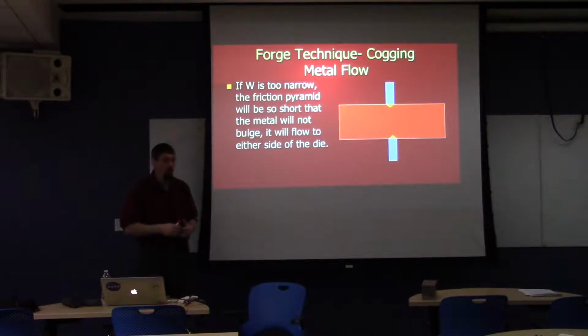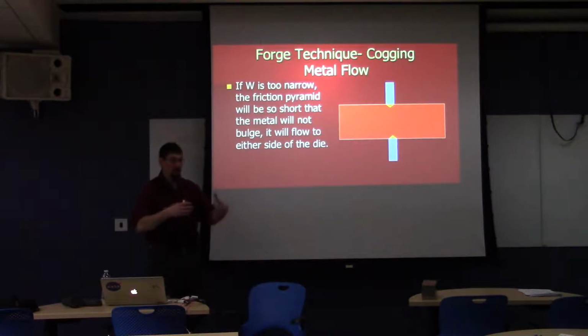If I get it down to a 40-inch cross section, I can have that 40-inch cross section at the maximum forging temperature, bring it to the press, and use a 30-inch die bite. Now my die bite is actually more than half the stock cross section, so that's helping me out. And if I can get a 20% draft, which I may be able to do at 40-inch cross section that I couldn't get at 60-inch cross section, now I'm working the center.